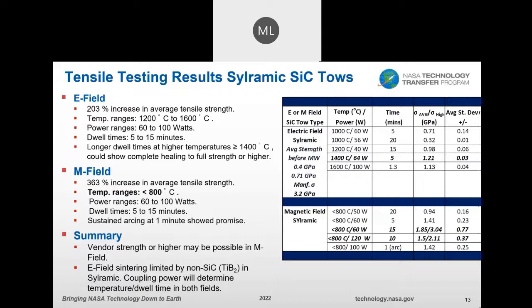But you can see that in the magnetic field, when you look at the table, we are reaching strengths that exceed, or getting close, actually 3.2 GPa of the actual strength of the ceramic of the vendor strength. So we believe that we can reach these higher strengths. So the vendor strength or higher may be possible.